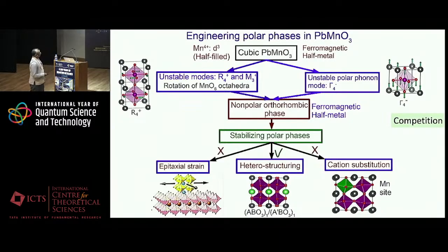There are many possibilities, but we find that there is usually a competition between rotational modes. Rotations means the MnO6 octahedra rotate out of phase or in phase, versus the dipolar moment, which is the polar phonon at the gamma point. And this competition stops this from becoming polar at any cost. So we tried 3 different routes to make it polar. One was to try epitaxial strain, where experimentalists can grow these films on a substrate and engineer the in-plane lattice constant. Second was cation substitution. You can substitute manganese with other transition metals, or you can use heterostructuring. What Manda talked about was van der Waals heterostructure.